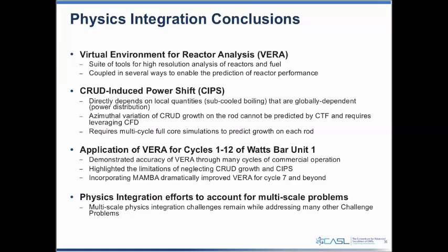So we talked about the application of VERA for cycles 1 to 12 of Watts Bar Unit 1, demonstrating the accuracy of VERA through many of those cycles, but really highlighting the limitations that neglecting crud can have in some of the cycles where there were problems. By doing so and incorporating Mamba, we dramatically improved the VERA solution in cycle 7. So many of these multi-scale physics integration challenges remain for the other challenge problems, and continued work is ongoing with regard to the crud modeling of this multi-scale problem.